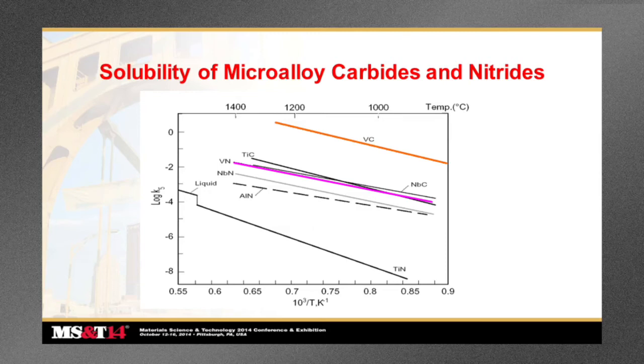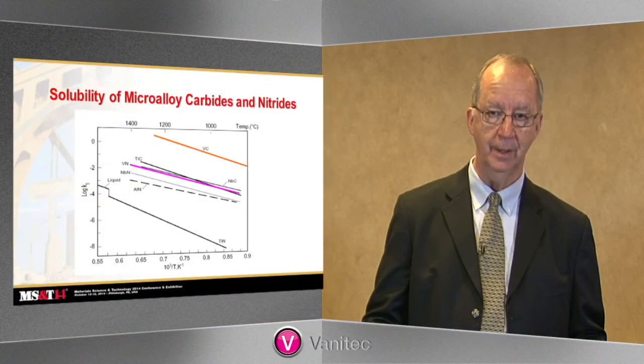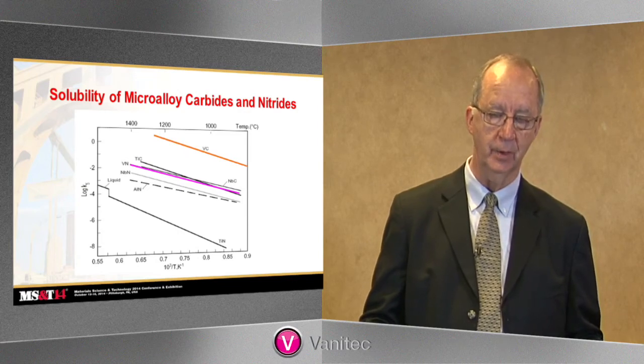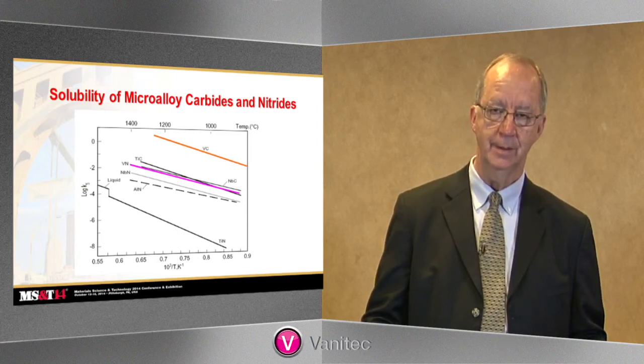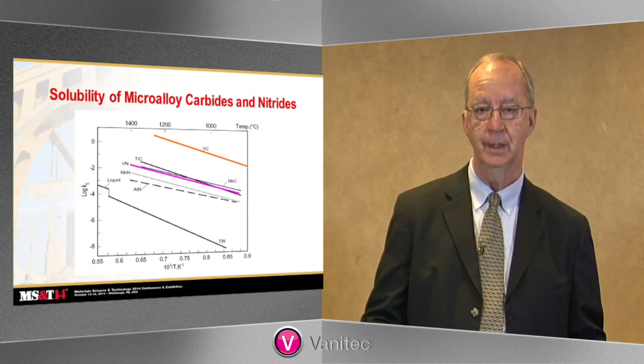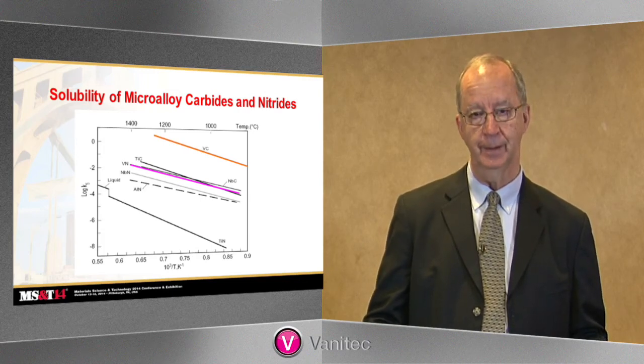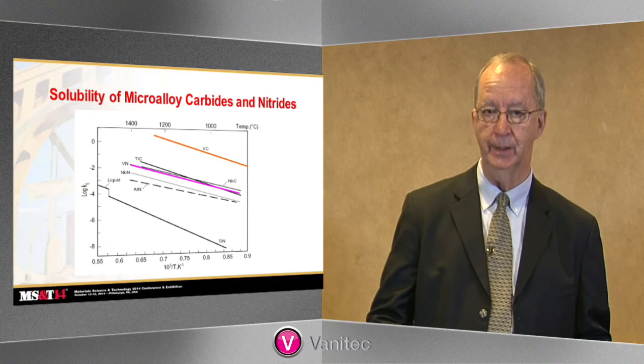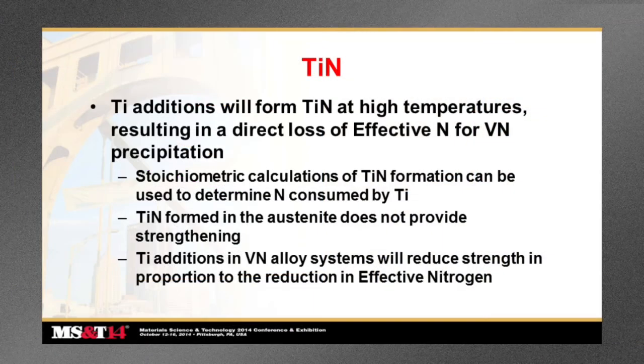So what this quickly shows you is that you are at high risk. If you have any of the other microalloys contained in the steel along with vanadium, you are at high risk of losing that nitrogen to a competing element. So when you look at this strengthening model that we just developed, you must ask what nitrogen is truly available here. You have to look at the prior processing history and determine how much nitrogen is actually available to precipitate with the vanadium nitride, and from that then you can predict what kind of strengthening you might expect to see. Let's look at each of these elements specifically.